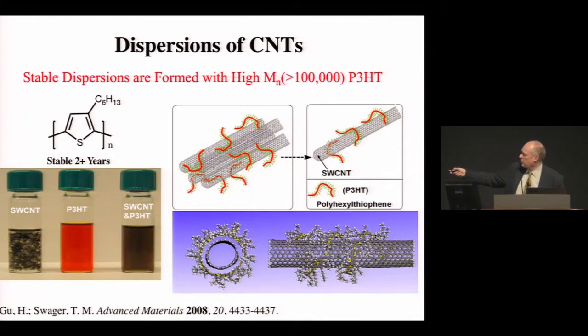And notice that the nanotube is not binding covalently to it, it's just physadsorbed. And if you do this with high molecular weight thiophene, you can make things that are stable for years. So this was great because we were working with engineers, and we would prepare a sample and they would say, okay, we're interested in printing this, but we might not get to it for a month. And you leave the sample with them, and the sample has to be good a month later, okay?